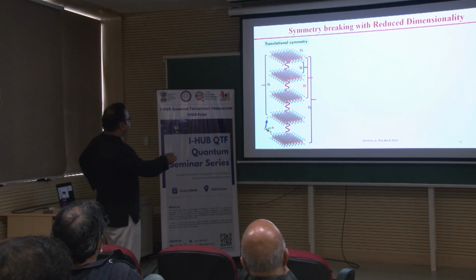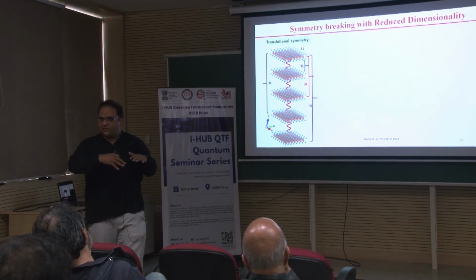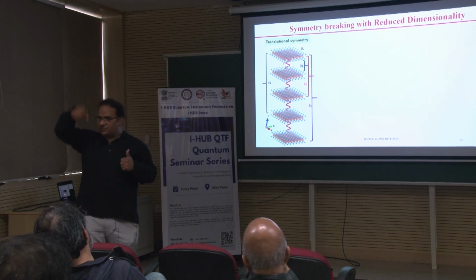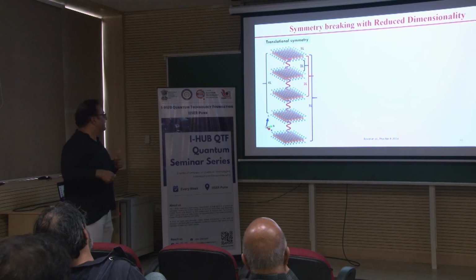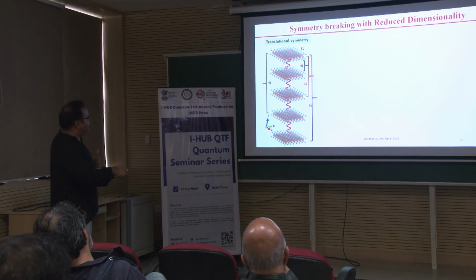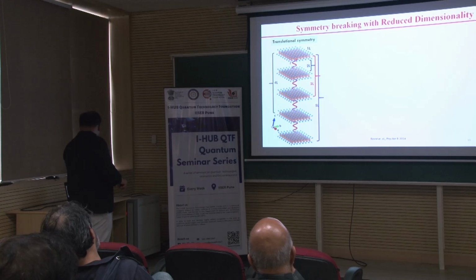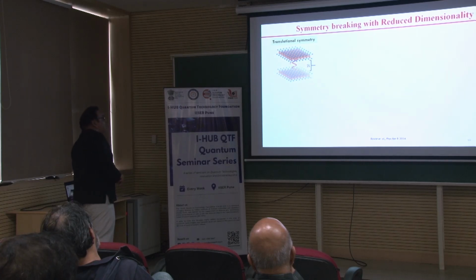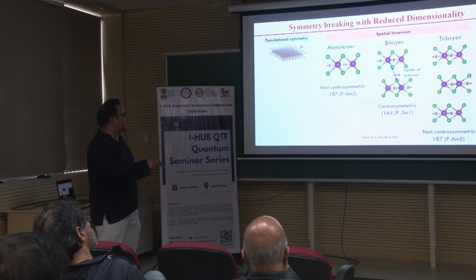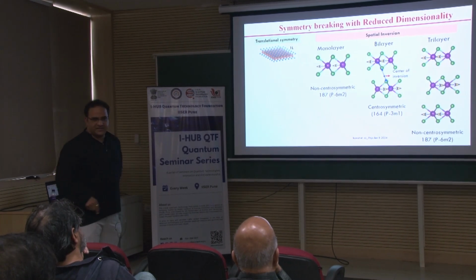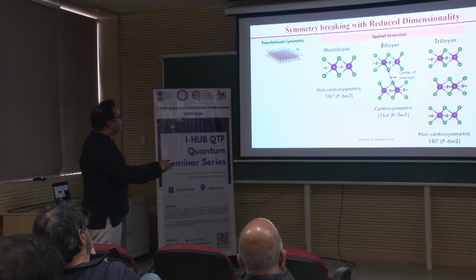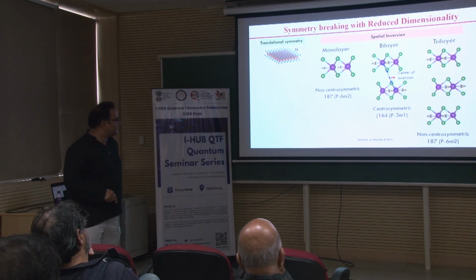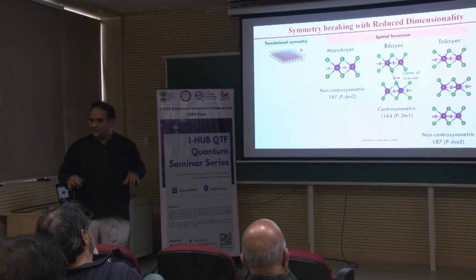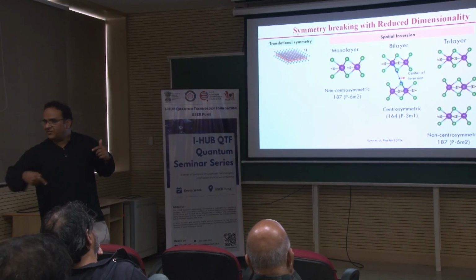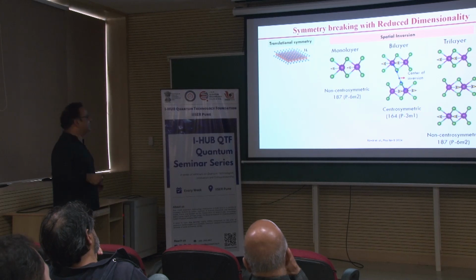Number 1, I am slowly taking out the top layer from there, okay. So number 1, my restoring force in the out-of-plane vibrations is less, okay. Second, in the bulk you have a translation symmetry, and it remains the same. But if I go to the monolayer regime, from bilayer to monolayer, what happens is that if I have a trilayer, I have a non-centrosymmetric structure. If I have a bilayer, which is the case of a unit cell, I have a centrosymmetric structure. If I go to the monolayer, this is a non-centrosymmetric structure. So symmetry is changing with the number of layers you are either removing or putting up, either way you can think about it, all right.